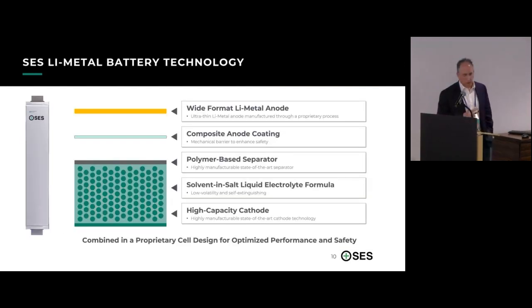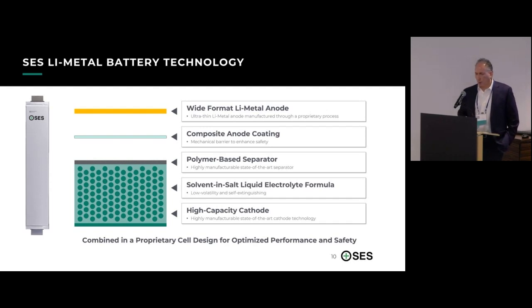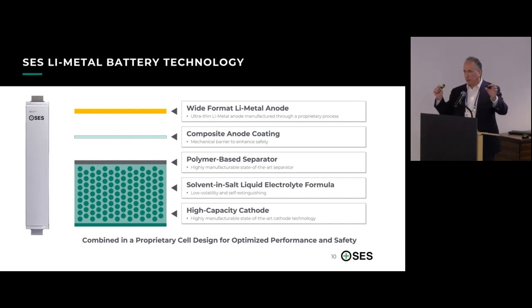Just moving on, this just breaks down our approach in a little bit more detail. You could see we have a wide format lithium metal anode. The lithium metal is basically extruded from a lithium ingot until it's down to about 20 microns in thickness, and it's a pretty wide format. We then laminate that onto a copper foil with proprietary equipment that was developed by the company, and that's how we form the anode. There's a composite anode coating, which is proprietary to SES.